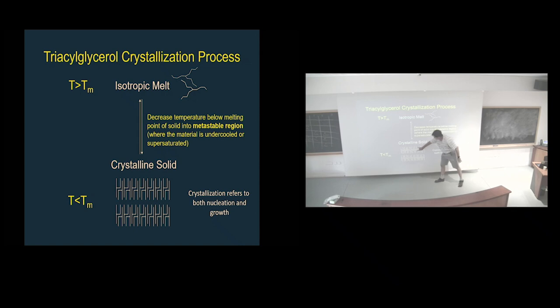And look how the crystalline solid is. Fairly easy. You have a long axis of the unit cell. These things are gigantic. We're talking like 40 angstroms. And these guys are like 3 to 4 angstroms. So you can really detect it in an X-ray diffraction pattern because you have this monster peak at very low Qs. And that is how big these lamella are. They stack in these sandwiches and sandwiches and sandwiches, and I'll show you what happens in a second.